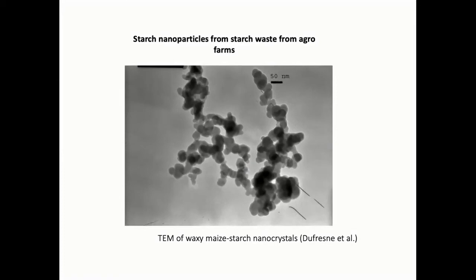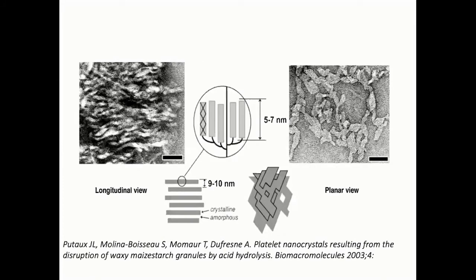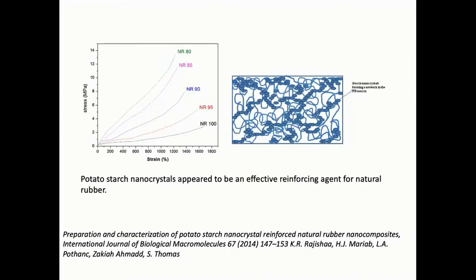And I want to show you nice work done by my PhD student, Rajisha. Rajisha took natural rubber latex, looked at the mechanics. You see, look at the modulus, natural rubber is a weak material. Modulus is low, especially modulus is low. Of course, it can undergo strain-induced crystallization and then the strength is high. But if you put increasing concentration of nanocrystals, 5, 10, 15, up to 20, you look at the improvement in mechanical properties. The modulus increases, the strength increases, without much sacrifice of extension. See, natural rubber extension is up to 1,600. But with 20% of nanocrystal, we got up to something like 1,200, pretty good.